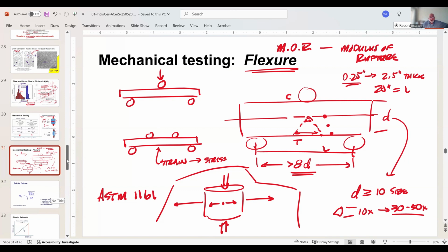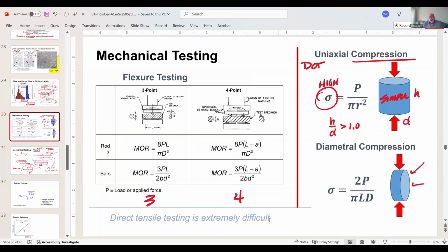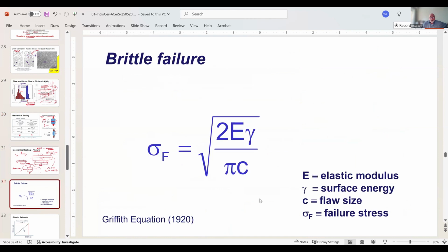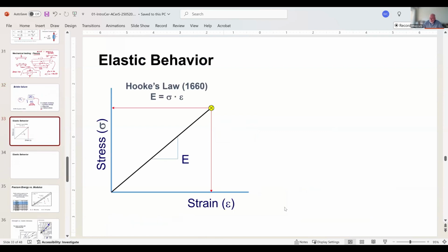All right. I mentioned tensile testing here just briefly. Direct tensile testing is extremely difficult because of how I grip my sample: the failure occurs at the grip, not where you want it to occur. So Griffith, 1920, came up with this equation. The failure strength of the system is equal to the square root of 2 times the elastic modulus times the fracture surface energy, divided by pi c. The 2 is there because I create 2 new fracture surfaces when the piece breaks. The c has to do with the geometry of the flaw, which we are going to ignore for today. So let's go into this in terms of what's really going on.